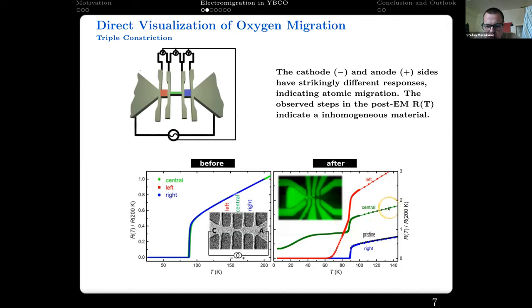have increased normal state resistance, but keep at least a small transition at 90 Kelvin, showing a probable inhomogeneous transition in the material. This image here was taken after a significant electromigration, so this one was somewhat gentle, but you can see that there is a clear difference in optical reflectivity of the electromigrated side of the material and the not electromigrated side of the material. So there is a number of properties that change in the material, and we have clear evidence that there is a movement of oxygen, that is of vacancies towards the cathode and oxygen atoms towards the anode.